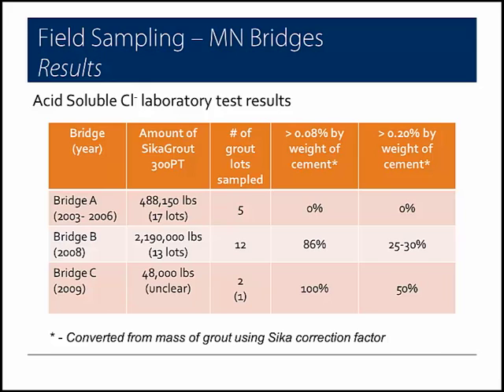Bridge C, built a year later in 2009, has only a limited amount of SikaGrout 300PT in it, although that number I'm not sure is confirmed. We attempted to target one grout lot for sampling, the one that was known to be in excess of 0.20% by weight of cement. Grout lot records were reviewed to identify which tendons we thought the grout lot was present in, and it turned out that we ended up sampling 2 different grout lots. We attempted to take 2 samples of the same grout lot, the one that was in excess of 0.5%.